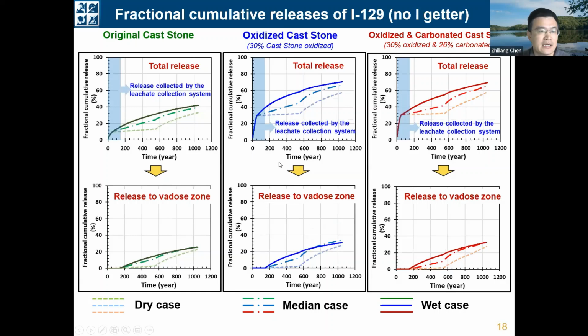And these are the results for iodine for the system without the iodine getter. Iodine is different from the technetium because the solubility of the iodine in the Cast Stone is much higher. So you can see the release from the original Cast Stone after 1,050 years is as high as around 35%, which is much higher compared to the release of the technetium. And also the oxidation and the carbonation will further increase the release rate by a factor of around 2.